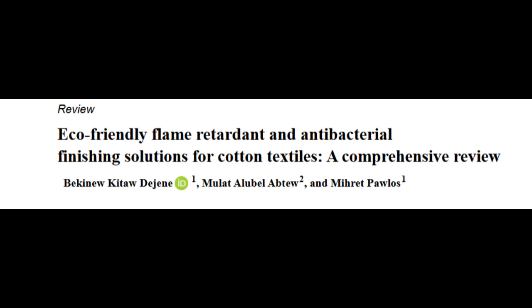Durability varies, though. That false banana sap treatment lasted up to 15 washes. 15 is okay, not 50, but still something. What about waste tea? That was interesting. An extract from waste tea leaves made cotton self-extinguishing in some tests. It significantly boosted the LOI and reduced the char length compared to untreated cotton. Why does tea work? Likely the polyphenols and tannins in the tea, great for char formation. But again, like many plant extracts, wash durability for large-scale use needs more work.